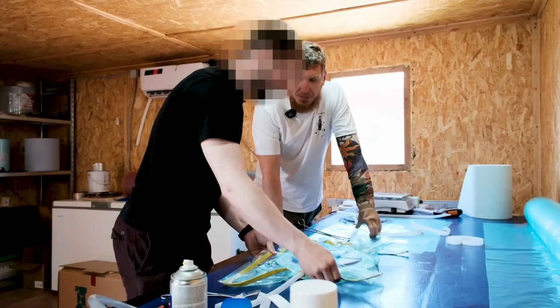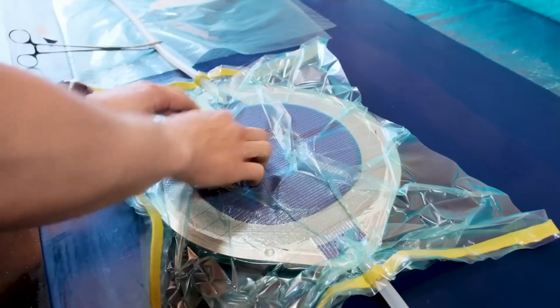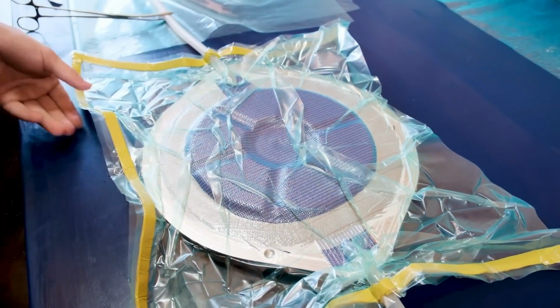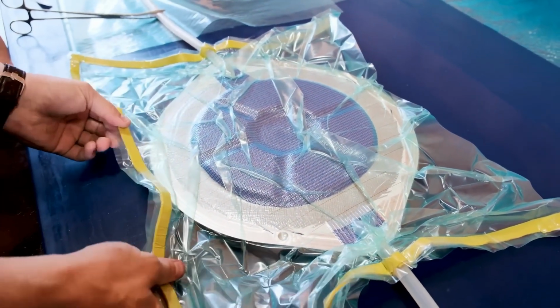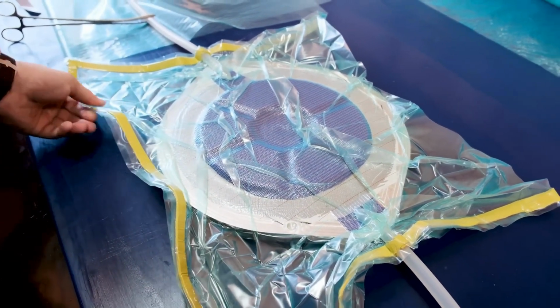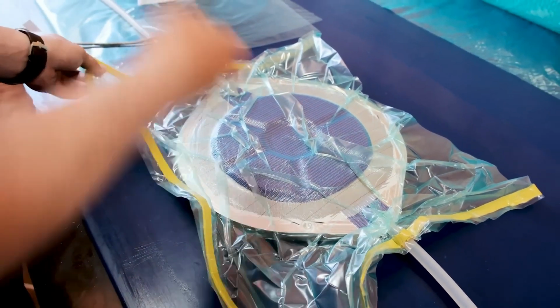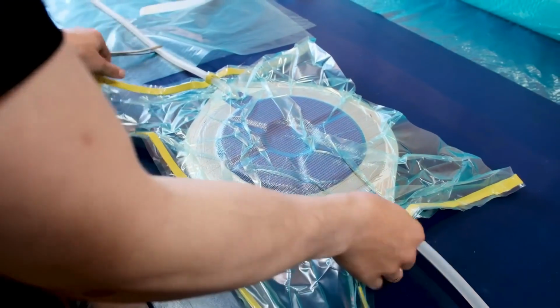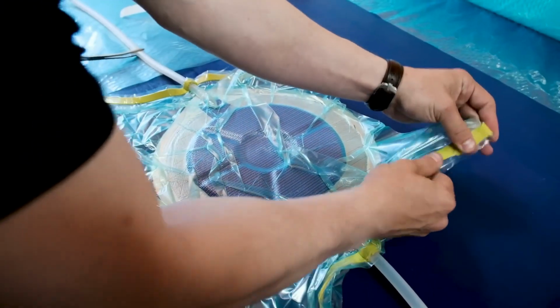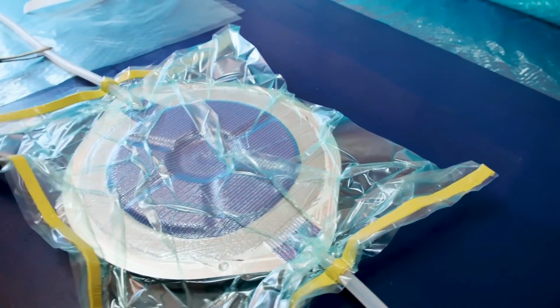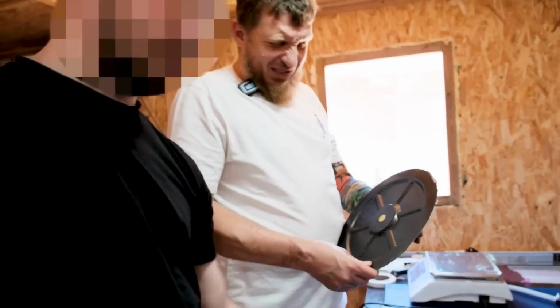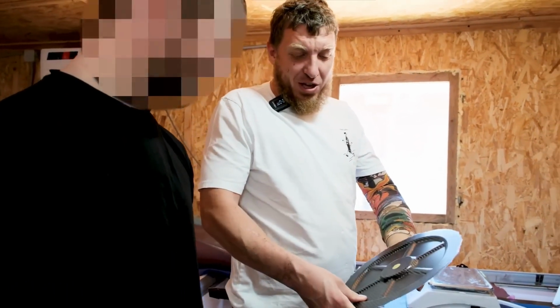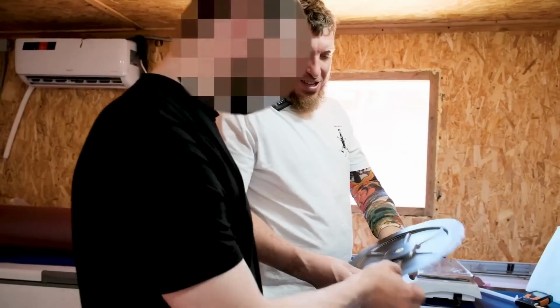There really shouldn't be any cavities at all, because any cavity, even a very small one, gets filled with resin, and that's basically a defect, since it's just resin without any reinforced fiber. It will eventually crack. But otherwise, in terms of strength, it's really rigid overall. But you really shouldn't actually jump on it. If you put the skin right on the edge here, that's what causes it. On the edge, yeah.